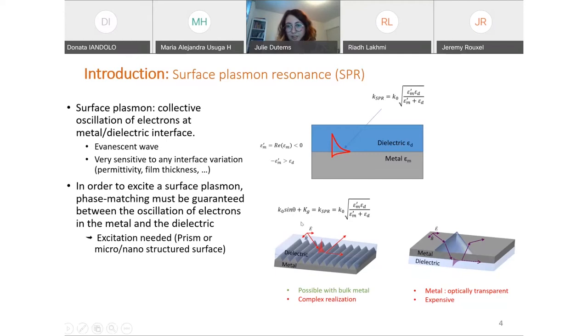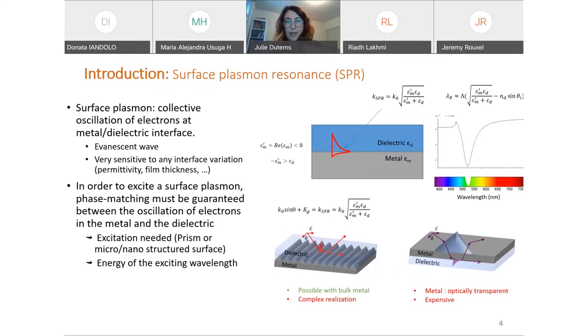An incident light will be incident on our grating, and some energy from the incident light will be used by the plasmon to propagate. The reflected light will be observed, in the case of a white light, by a spectrophotometer, giving what is called here a plasmonic dip. And we will observe the light minus the wavelength associated with the energy that has been used by the plasmon to propagate at the interface.